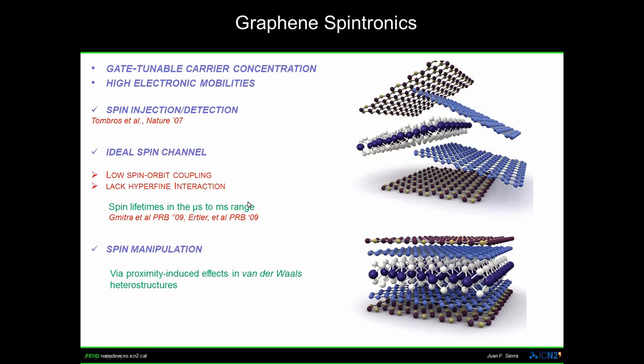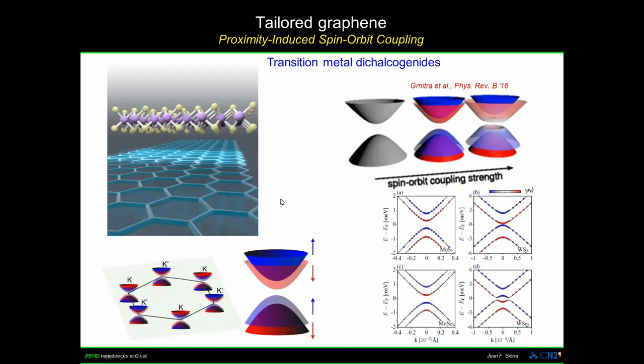Let me explain what happens when you bring graphene together with a transition metal dichalcogenide. The first thing that occurs is that due to the breaking of pseudo-spin symmetry, you open a gap in the graphene band structure in the millielectron-volt range while keeping the linear band structure. The second consequence is that the combination of spin-orbit coupling brought by the transition metal dichalcogenide together with the breaking of space inversion symmetry removes the spin degeneracy — you get spin splitting in the bands.